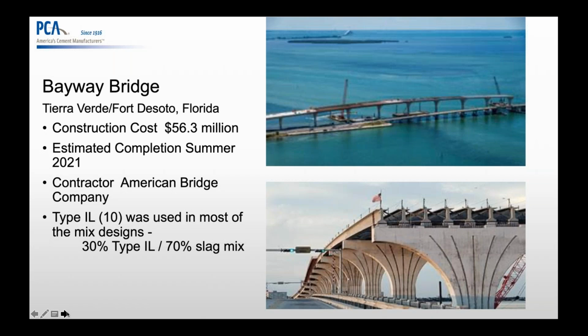This is an ongoing project, and you can even drive by it. They're using Portland limestone cement at a rate of 30% and 70% slag mixes. These concrete mixes are used that way to mitigate the heat of hydration of the concrete, because there's a lot of mass concrete in this project, and some other structures as well.